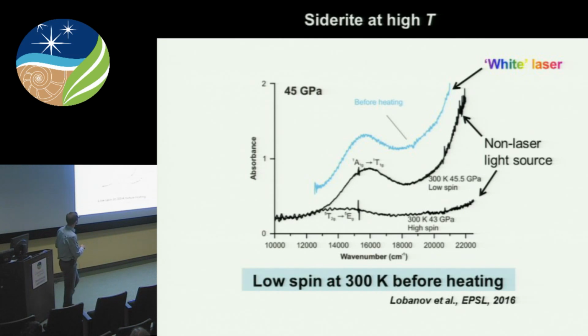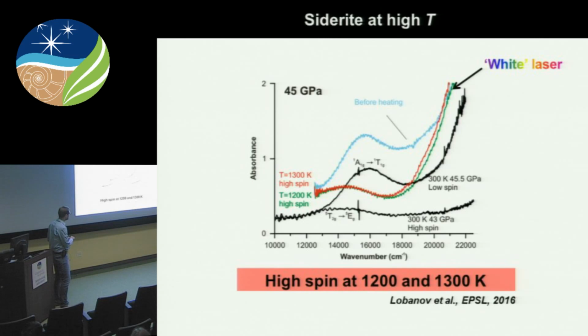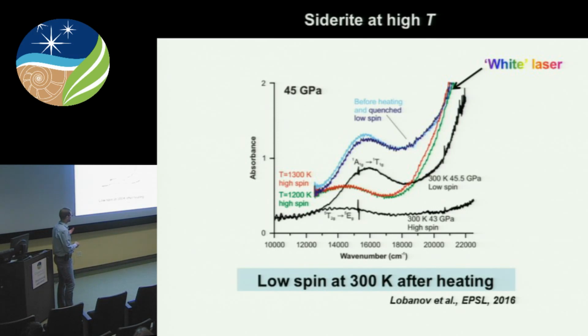So this blue absorption spectrum was collected with the white laser method, the new method that I have described. And the black spectra are the absorption spectra of siderite taken in a different run with a conventional optical setup. So you can clearly see that at 45 GPa, our absorption spectrum corresponds to the low spin siderite. But once we heat it to 1200 or 1300 Kelvin, this intense absorption band is no longer present, and instead you have this weak feature that clearly tells us that we are looking at the high spin state at high temperature. Once we shut down the heating laser and collect this absorption spectrum again, we see that the transformation at high temperature is completely reversible.